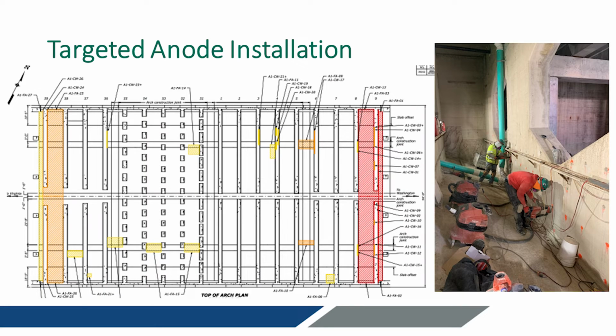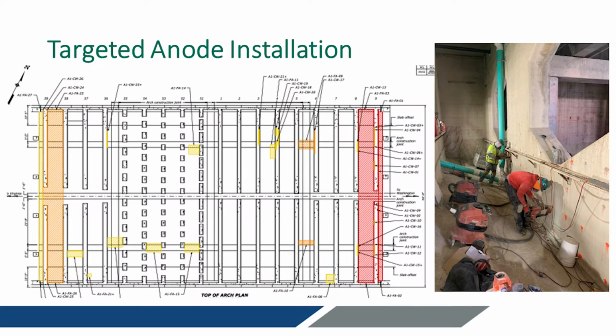So here, this is a plan view of one span. You can see these are the cross walls here, and you can see the hatched areas on either end. Effectively, at the end of every arch there are expansion joints, and as we all would suspect, at the expansion joints there's a lot of chlorides getting in. So the risk for corrosion in those areas was quite high. So we're targeting a lot of those areas. But outside of that expansion area, we're really just targeting some small localized areas where maybe there were cracks in the deck or leaky joints or something that got in there. So you can see this is a quite large bridge, but we're really only putting CP in a small portion of the whole structure.